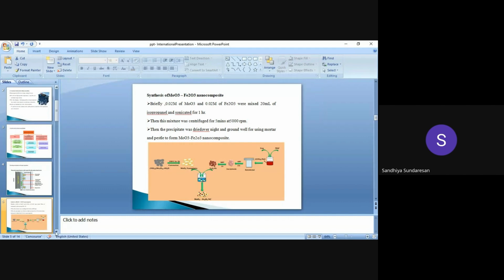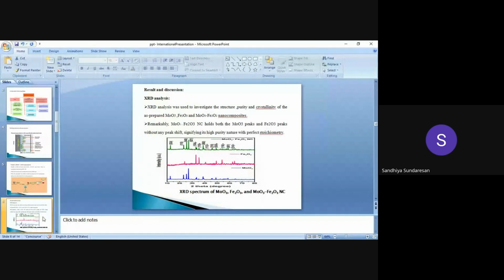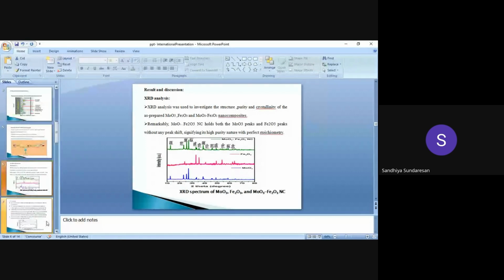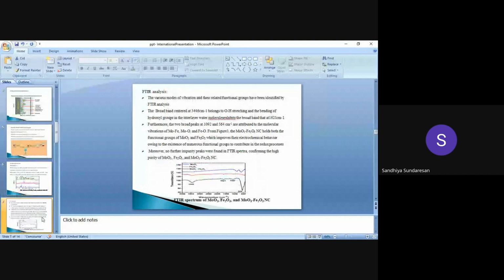oxide nanocomposites. And this is the XRD analysis, used to investigate the structure, purity, and crystallinity of the prepared molybdenum trioxide, iron oxide, and these composites. Without any peak shift, signifying the high purity nature and perfect stoichiometry. This is the FTIR analysis. The broad band centered at 3,446 cm^-1 belongs to O-H stretching and binding hydroxyl groups. And the interlayer water molecules exhibit the broad band at 1621 cm^-1.